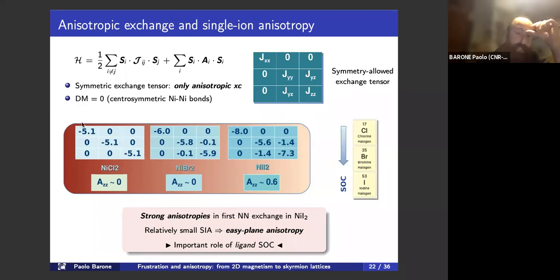The second thing is that going down in the column of halogen atoms, we move from the chlorine case, where basically there is no anisotropy, at least within our numerical accuracy, we couldn't find any anisotropic term in the exchange, nor in the single ion anisotropy. But already in the bromine case, we start to see a non-negligible anisotropy in the exchange, while there is no single ion anisotropy. And finally, in the iodine case, the effect is really, really strong.